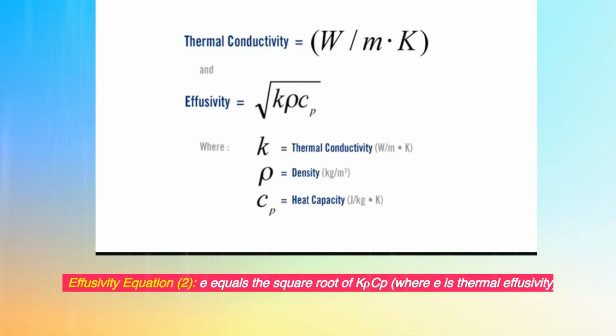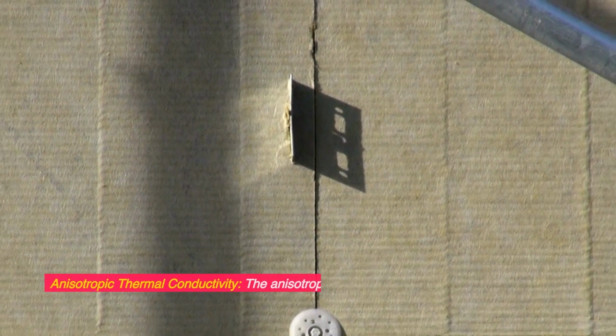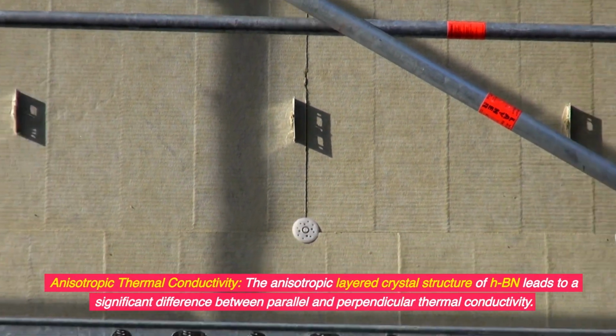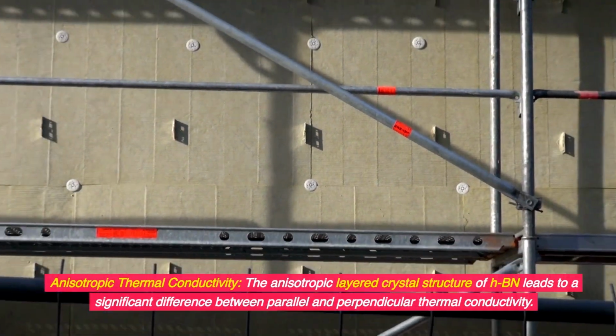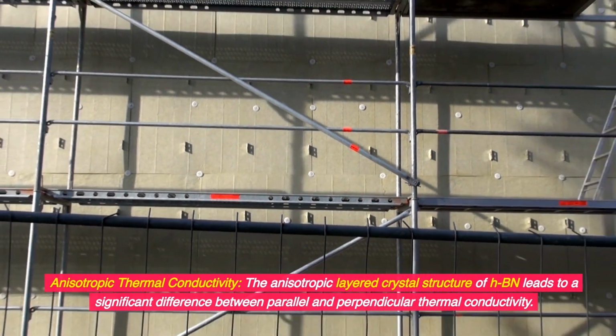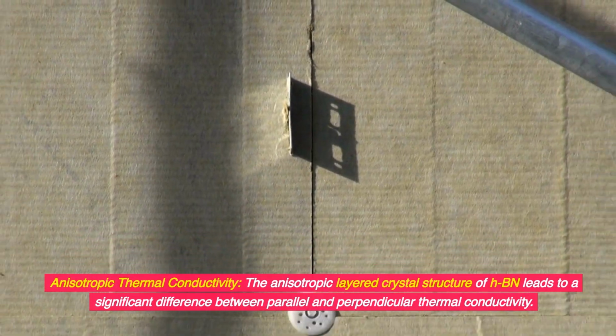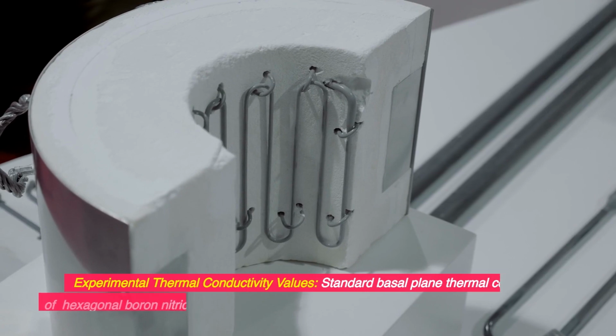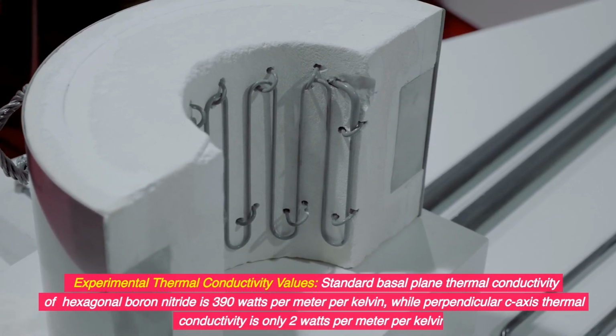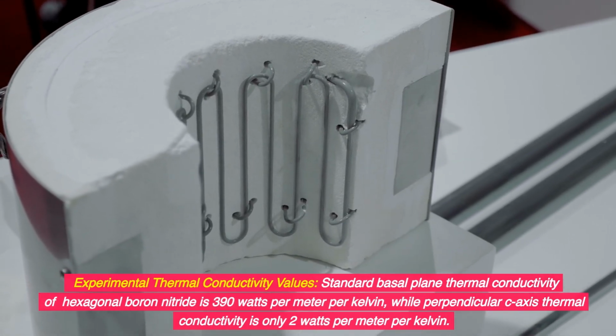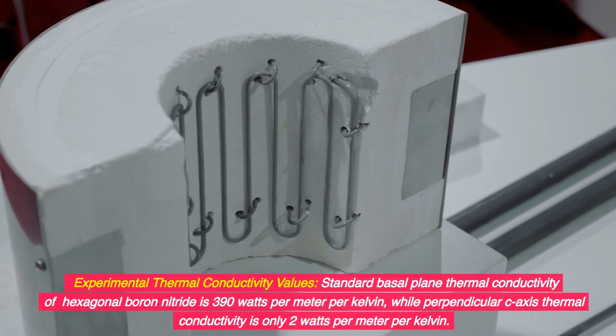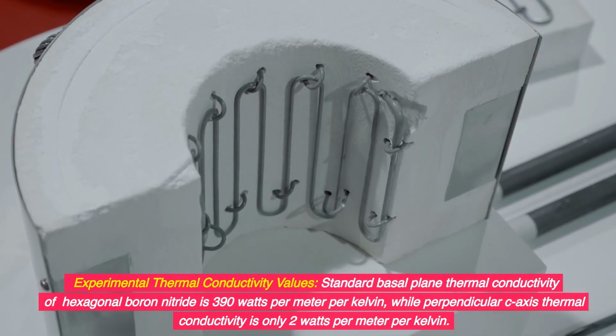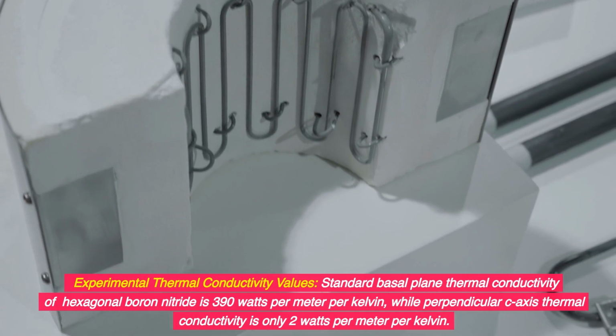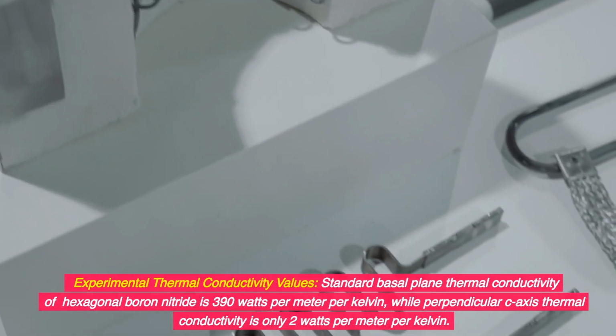Effusivity equation, 2: e equals the square root of k rho Cp, where e is thermal effusivity. Anisotropic thermal conductivity: the anisotropic layered crystal structure of HBN leads to a significant difference between parallel and perpendicular thermal conductivity. Experimental thermal conductivity values: standard basal plane thermal conductivity of hexagonal boron nitride is 390 watts per meter per Kelvin, while perpendicular c-axis thermal conductivity is only 2 watts per meter per Kelvin.